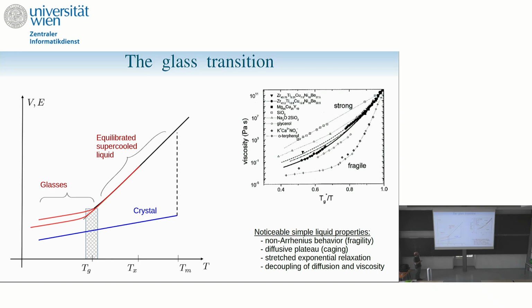It's really the objective of many research papers to understand the fragile behavior of supercooled liquids. Then when you continue to cool down, you see that the volume no longer reduces. What happens here is the system falls out of equilibrium, so you can no longer equilibrate. If you do a thermal ramp at a certain speed, you obtain a curve like that. If you cool down more slowly, you might follow the liquid behavior to a bit lower temperature and then fall out of equilibrium a bit lower. So the glass transition depends on rates, because the system is trying to relax, and the relaxation times become arbitrarily large at experimental timescales.